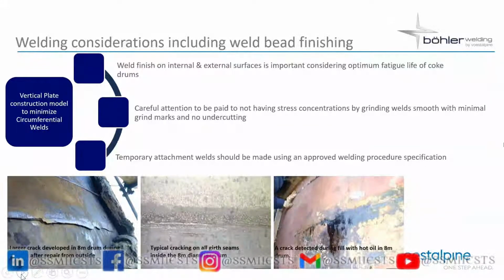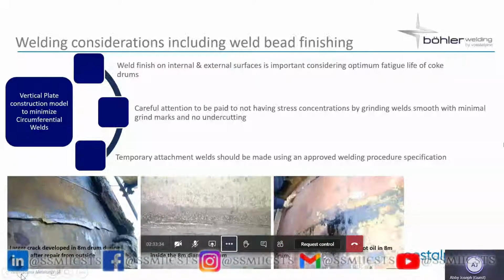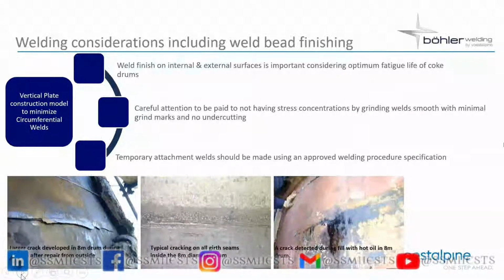And so you have the mapping of the plates, you have the consumables which are matching, but after that, during the fabrication, there were many more constraints, like the weld finish, to make sure that there were no stress concentrations, to make sure that the weld finish was extremely good, to improve the fatigue life of the coke drum. And we talked about thermal cycling in the beginning. Also here there was an additional requirement that even for temporary attachments, an approved welding procedure specification had to be qualified before allowing even temporary attachment welds to be made during fabrication. Next.